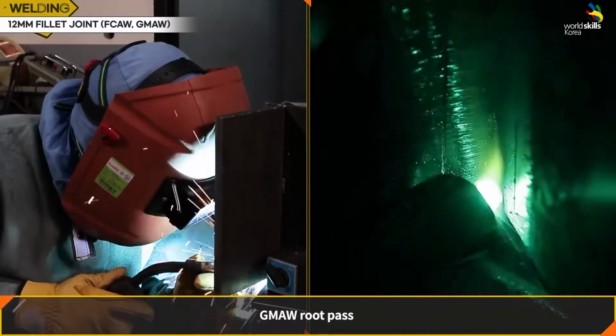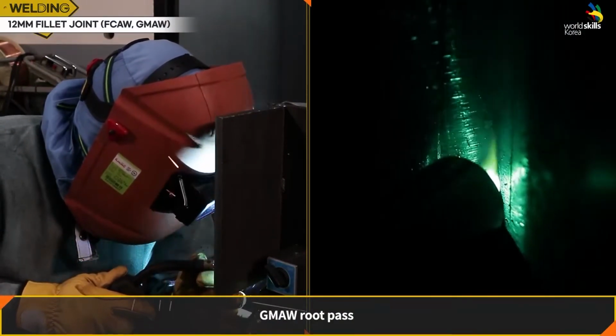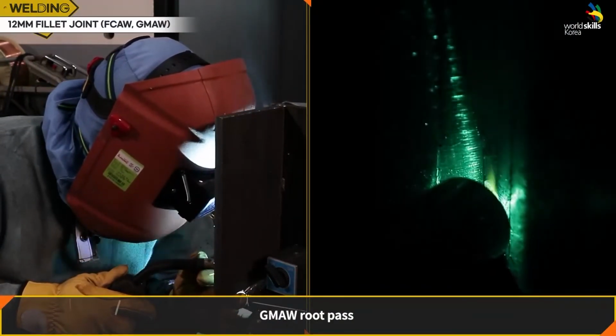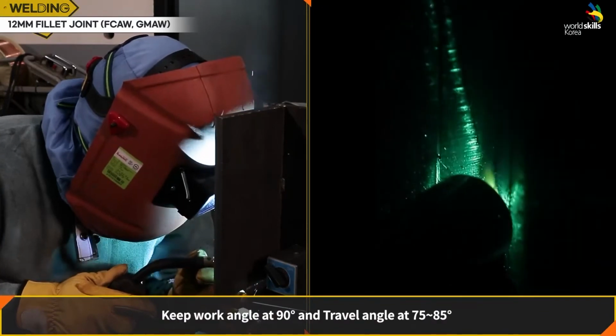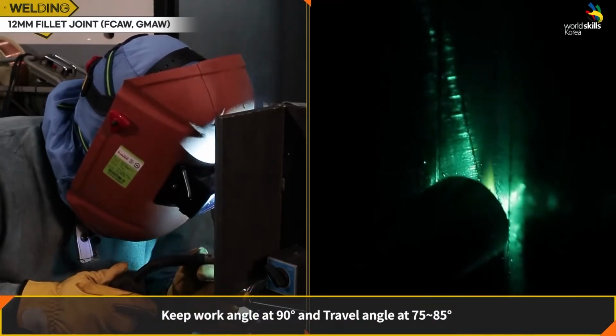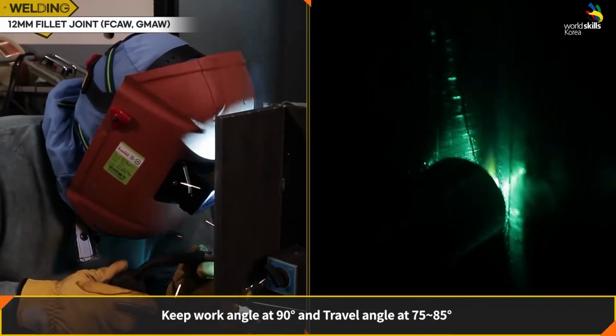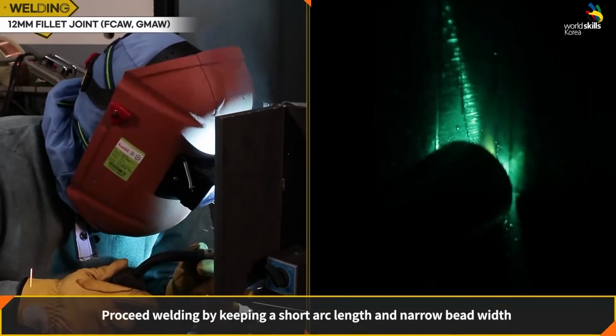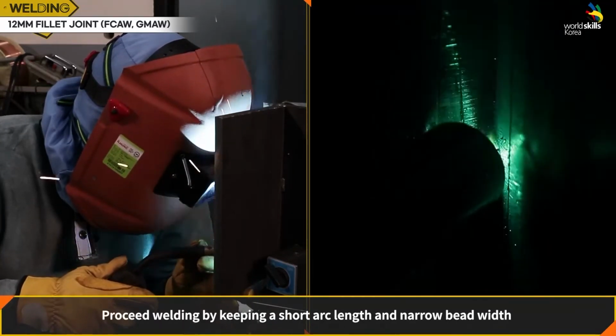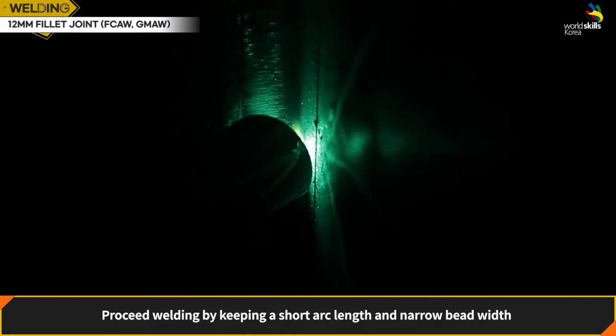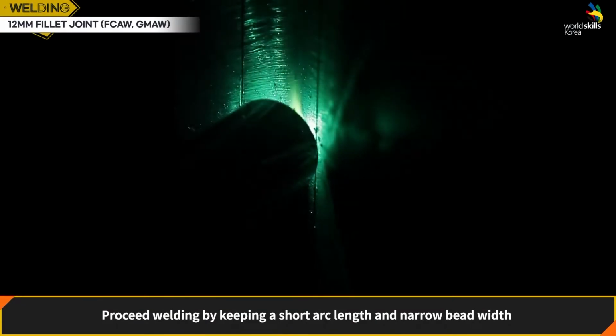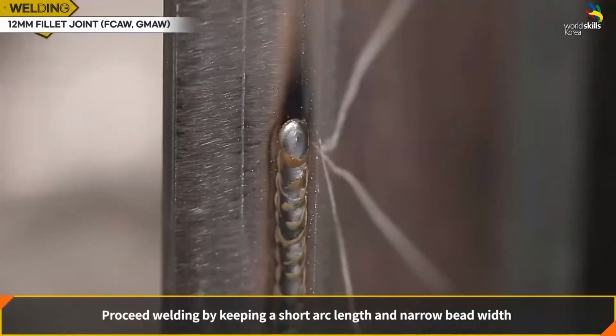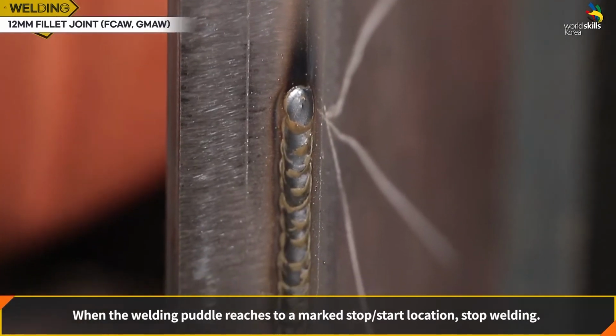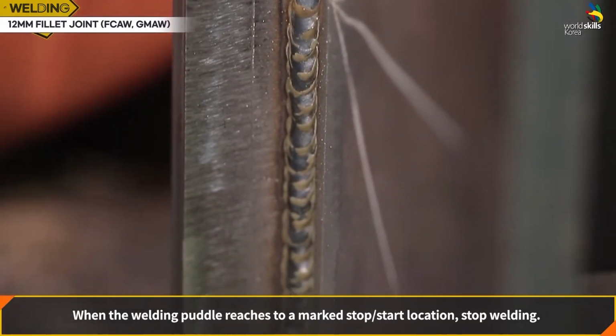GMAW vertical position root pass. Keep the work angle at 90 degrees and the travel angle at 75 to 85 degrees. Proceed with welding by keeping a short arc length and narrow bead width. When the welding puddle reaches the marked stop-start location, stop welding.